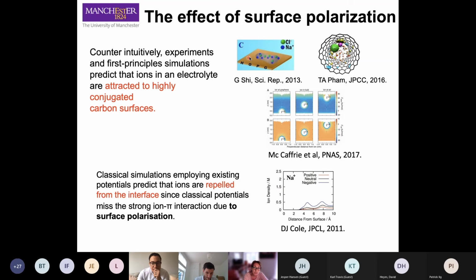This is a cartoon describing STM experiments, for example, with HOPG, which is this highly ordered pyrolytic graphitic surface, and these should be the ions of the electrolyte. These are experiments instead with spectroscopic measurements. They both show that there is adsorption of ions on the surface of graphene, even when it is very mildly charged. And this is an ab initio molecular dynamics simulation performed on carbon nanotubes with, again, an electrolyte that has been pushed through it. And again, this ab initio NEMD showed that there is adsorption of ions.